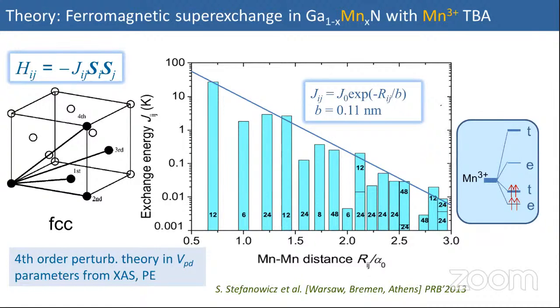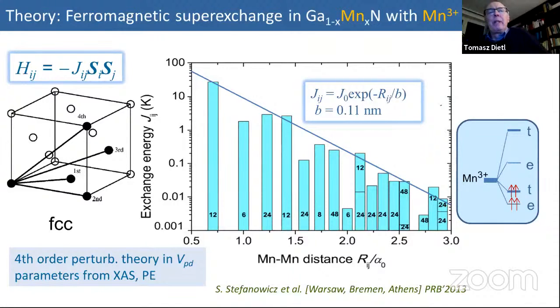And the same question for the holes, for the PD. So for the holes, we know this from photoemission and XAS. We see how the hole interacts with manganese, and we can determine this parameter. We know it's larger compared to other materials because, of course, it scales with distance, and here distances are very small. In the case of gallium nitride, the lattice constant is very small. So you have a little larger beta, if you know what I mean by beta, this PD exchange integral. It's relatively large in gallium manganese nitride.